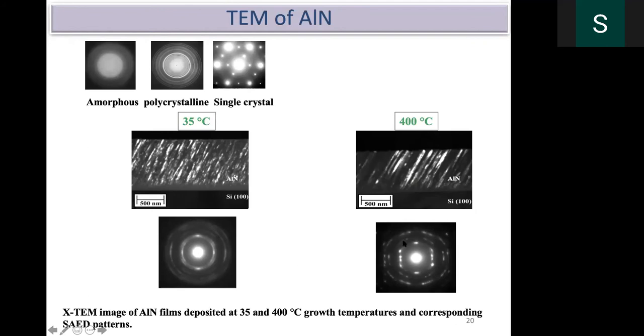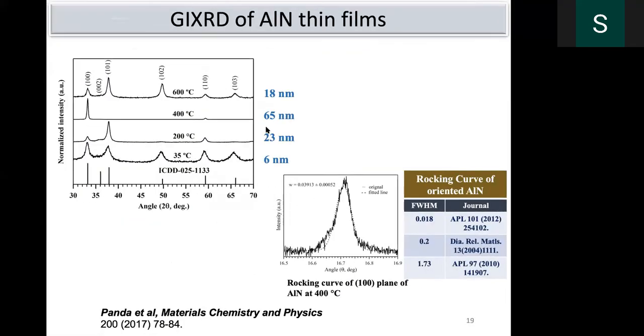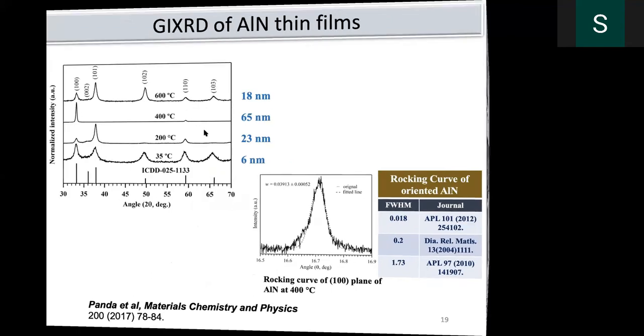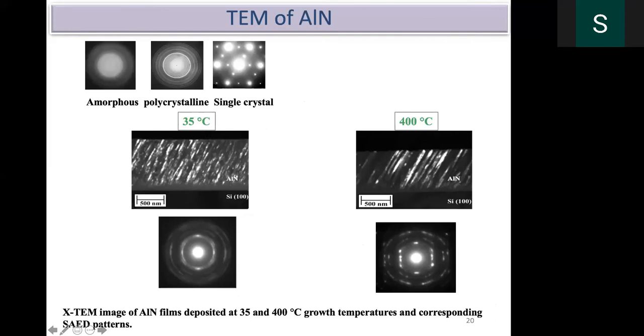But in this case, you can see some particular orientation exists. That means it has both the 100 orientation and some other orientation coexisting. That's what we can understand from this X-ray. There are two peaks coexisting. So from this we can understand that the crystal grown at 400 degrees centigrade is oriented in a particular direction.